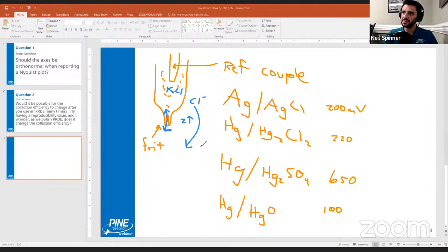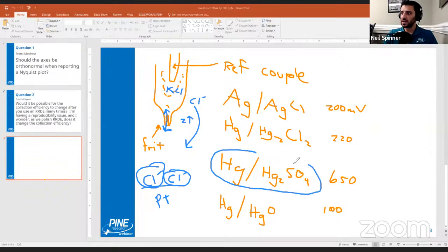But for people who are doing very sensitive kinds of tests, especially with things like platinum or palladium, chloride has this tendency to plug up active sites on platinum. So it's like you have your platinum electrode and it's doing whatever reaction you're doing on it. Well, chloride has this tendency to block it. It'll sort of clog the platinum. It reduces its electrocatalytic activity to some extent. And so a lot of times you're trying to avoid chloride getting in the way at all, so you might use something else. You might use a reference electrode that has sulfate, right? Sulfate is less interfering. So those are some of the considerations as well.